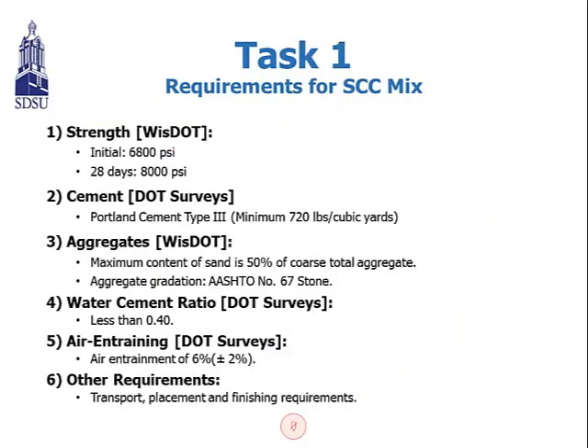After that, we present and discuss the survey result to the Wisconsin DOT project panel, and we reflect the feedback from the project panel and decide the requirement for the SCC mixture to be used for the PSC girder for Wisconsin DOT. The finalized requirement for the SCC mixture can be seen in this slide. For example, initial strength must be equal to or more than 6,800 PSI, and after 28 days curing period, the strength must be more than or equal to 8,000 PSI.